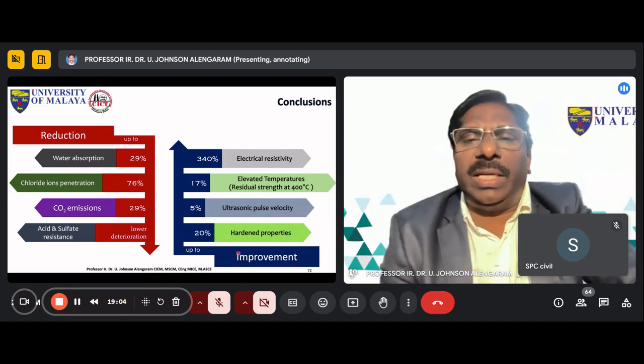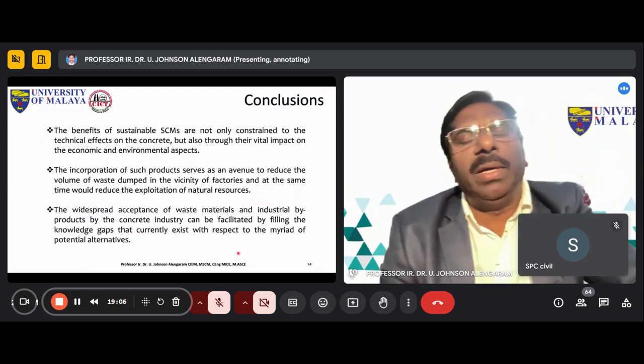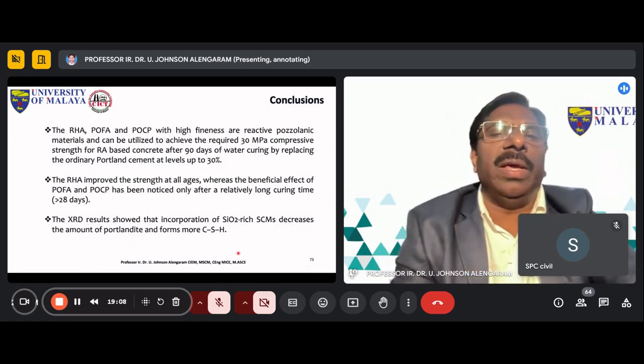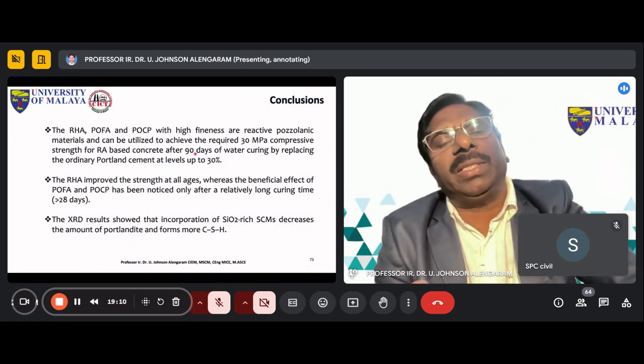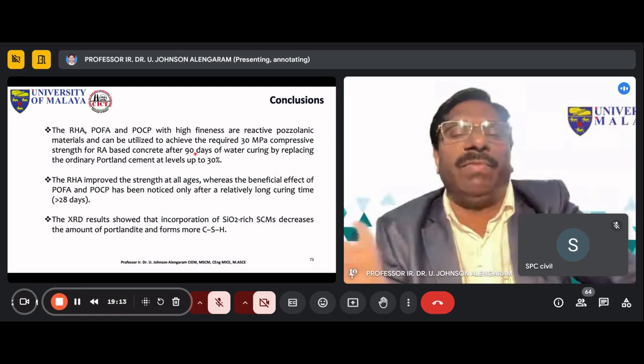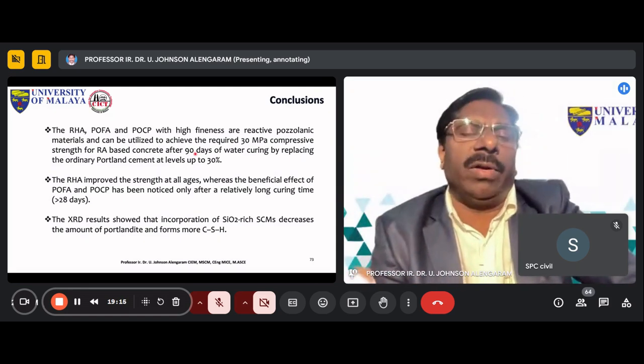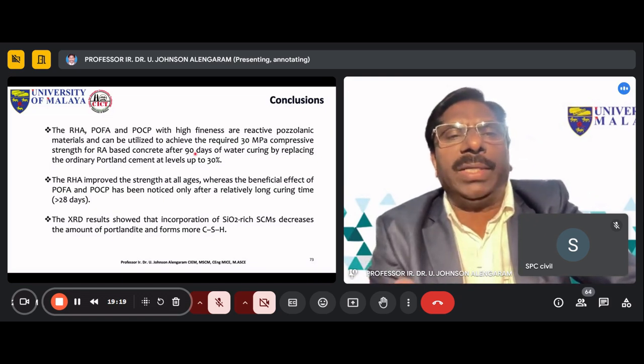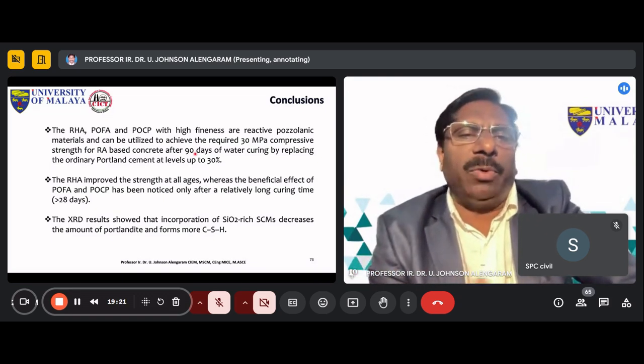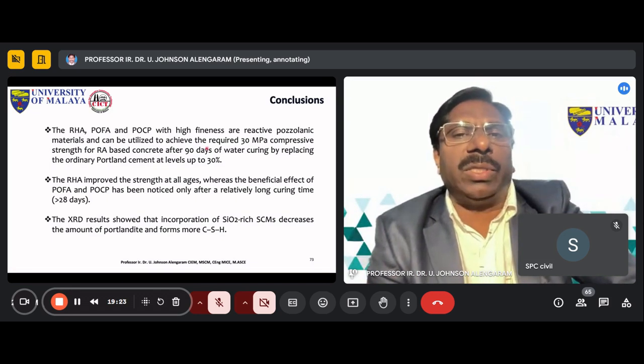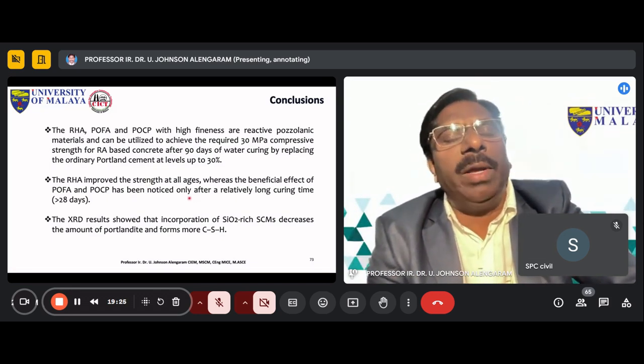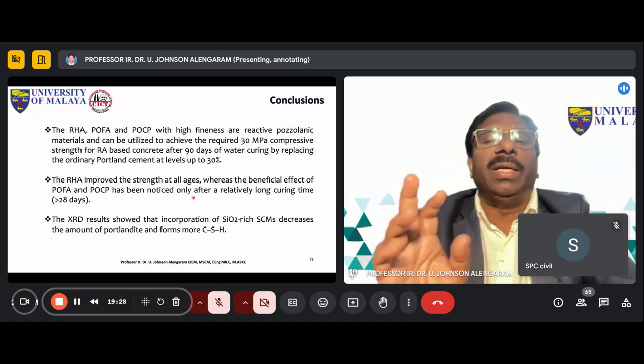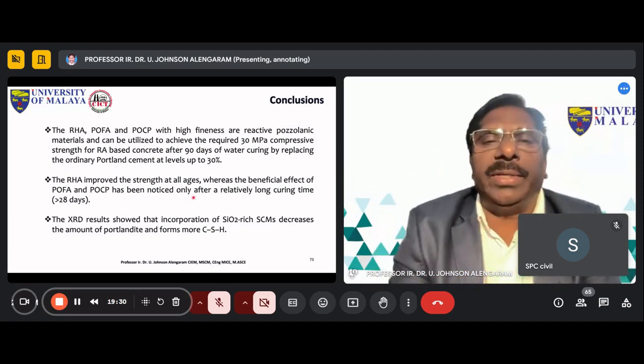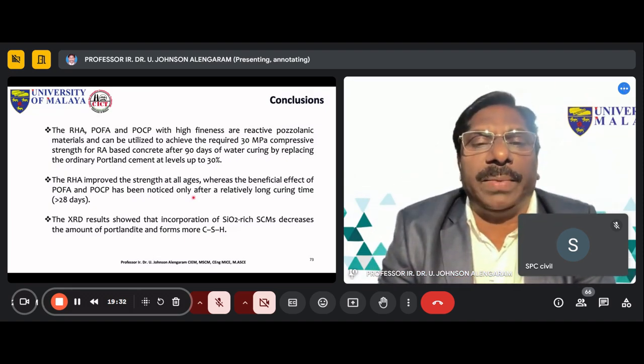So this is generally what we have achieved from the usage of the supplementary cementitious materials. Some are traditional, some are non-traditional, but we use non-traditional here. What are the non-traditional? We use rice husk ash, we use palm oil fuel ash, and we use palm oil clinker powder. Up to 30% is possible, but we recommend up to 20% because of the durability aspect. 30% is not good, but 20% is good for the durability aspect.